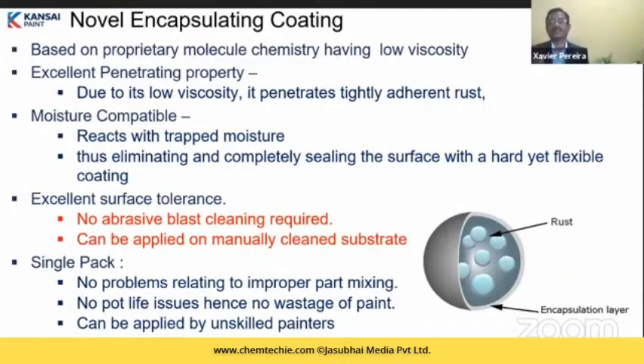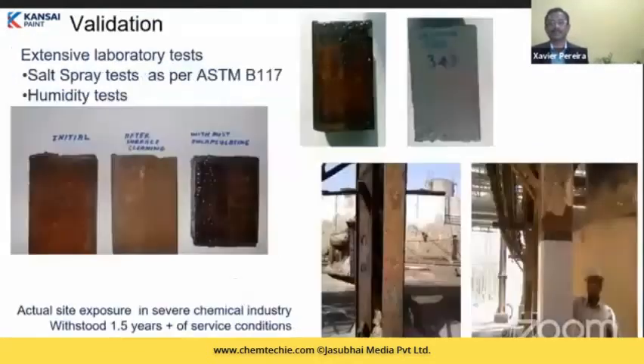Okay, now this polymer is moisture compatible. So when it goes and penetrates into the rust, right there, the tinge of moisture that is there, it reacts with the trapped moisture, thus eliminating it and completely sealing the surface with a hard coating. It has got excellent surface tolerance, so there is no abrasive surface preparation required. Only St2 grade is sufficient. It can be applied on manually cleaned surface. It is a single pack, and therefore there are no problems, because the job is done by unskilled laborers, so no problems related to part mixing. There are no pot life issues, no wastage of paint, and it can be applied by unskilled painters.